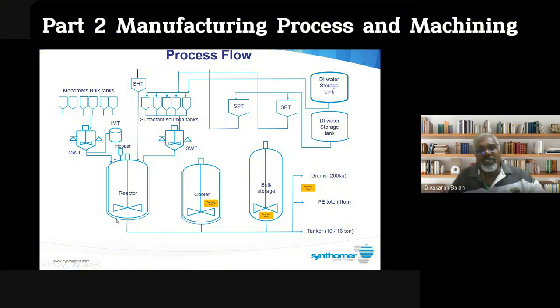Okay, on the reactor process here, and here SWT is the solvent weighing tank. This is a surfactant solution tank where we transfer the raw material. Some need to be pre-diluted, some can be pumped direct. We keep it in this small tank up here. When the reactor has downloaded the recipe, it will discharge whatever we need from this tank. This surfactant solution tank, you have like 16 units, so different tanks for different materials. Whatever we need will be charged to this SWT, solvent weighing tank, or surfactant weighing tank. The quantity, how much we need, it will charge here. Same, MWT will charge to IMT, how much quantity we need.